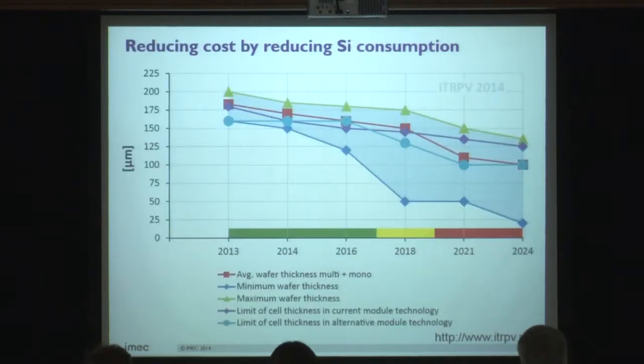So that's why, again, a figure from the ITRPV roadmap, it is clear that the industry wants to reduce the thickness. If you look at this curve in red, within 10 years, the industry wants to go to wafers with a thickness of only 100 micrometers. But you also see on this roadmap from ITRPV a blue curve, which actually goes much below 100 microns, even below 50 microns. So actually the roadmap keeps open the possibility to go even much thinner in the near future.